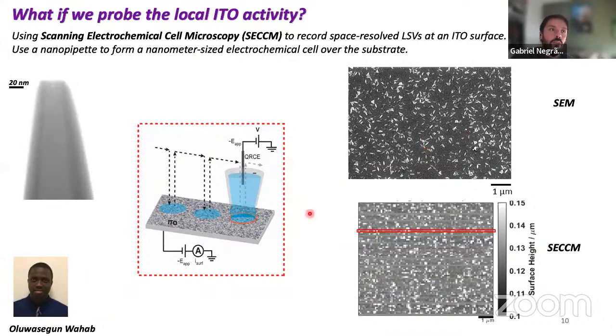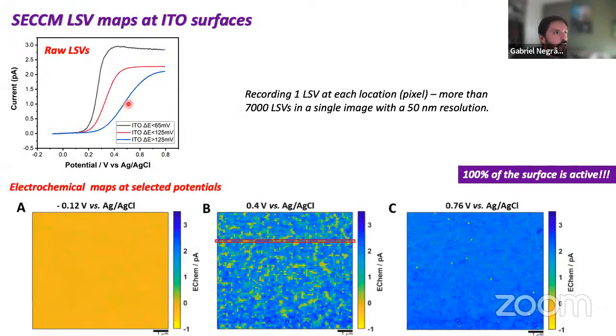But more importantly, how do the CVs look at every single one of those points? I'm showing you here a family of CVs, the first ones that I showed you on the slide. They all look like we expected: they have this plateau, we get to this steady state current. Some of them have different currents, and some have different inclinations. This is already hinting to us that there are different kinetics on the surface, because we have something here that's quite fast. Remember in my talk yesterday, I like to think of this as thermodynamic in a lot of ways, because it's the amount of energy I'm providing to the system and the kinetics aspect. There's a system here where I have to provide a little bit of energy and the reaction happens really fast. Another one where I have to provide a lot of energy, and even so the reaction happens very slowly. So this hints to us there are different kinetics on that surface.